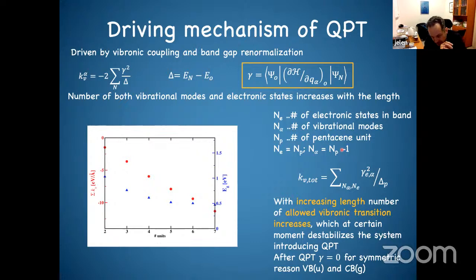But there is one more thing that I'm not showing here, but recently we also discovered that when you are very close to this phase transition and you start to do the simulations at finite temperature, you see that the system starts to jump from one phase to the other phase. So for example, if I have a system of 15 units and I put in temperature so the system can start to relax and vibrate, you will see the system jump or fluctuate between these two states. And of course this goes through the closing of the band gap.